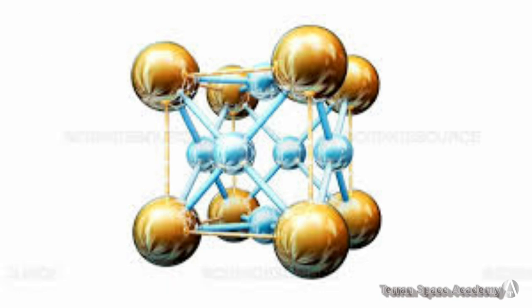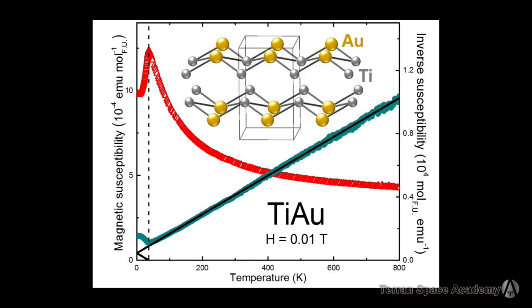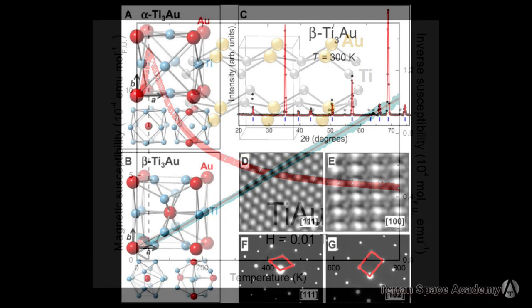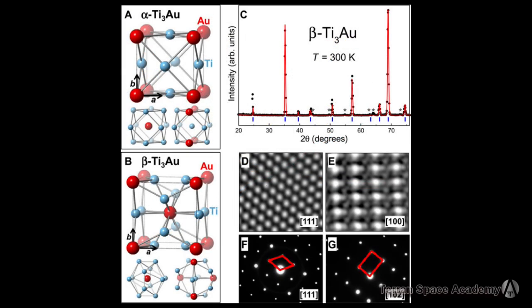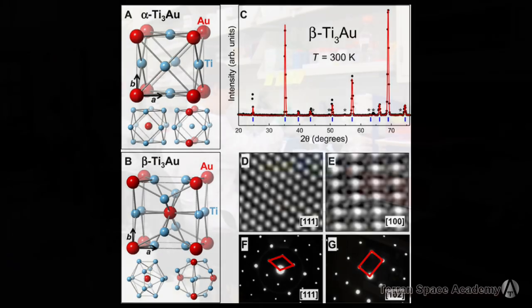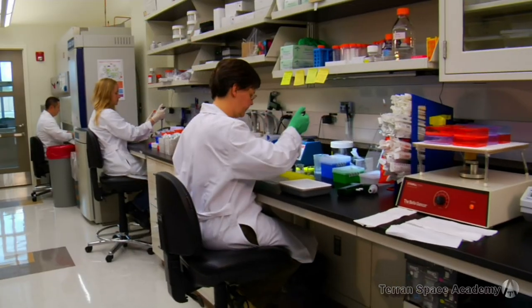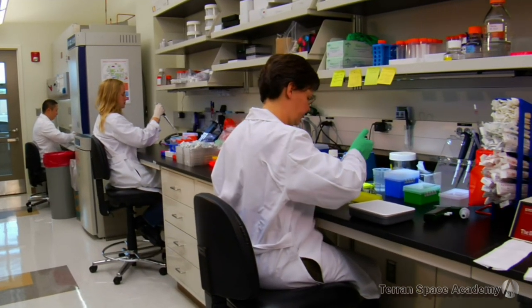Strange things happen with alloys. Scientists found that while both titanium and gold are not magnetic, a one-to-one alloy of these was. It was also found that if you mix titanium with gold at an extremely high temperature, it will form a beta version of its crystal when it cools. This beta crystal gives the alloy its extreme hardness. If it is heated to a lower temperature, it will form alpha-type crystals when it cools and be no harder than regular titanium. These discoveries were confirmed by scientists at other labs in Texas and Florida.